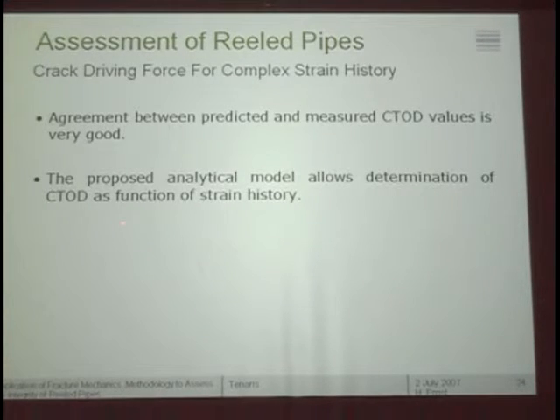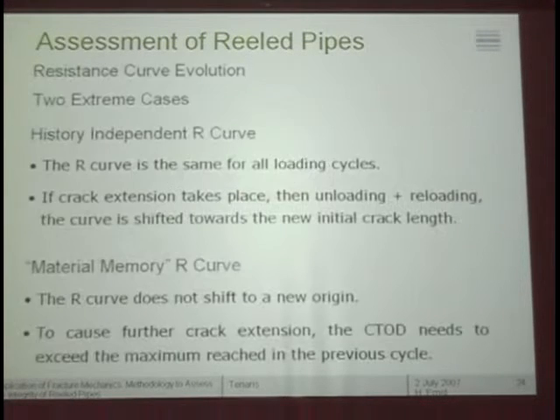And that allows us to continue on to the second part of this, because so far the only thing that we have done is to see the evolution of the applied CTOD. We have not said anything yet about how the crack grows in the first cycle or in the second cycle. To do that, we need to take a look at the resistance curve evolution. And we see there are two extreme cases. The one, if you want, is the history-independent resistance curve. This is the one that people have been using in the past, since they have not done all this.